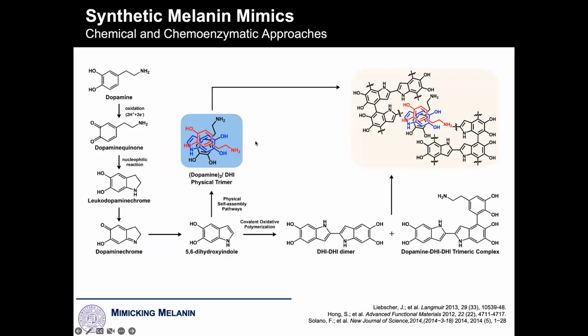We have two effects then. We have both covalent bond formation between these rings, and you can see some of the dimers and trimeric complexes that are forming. These go on to make tetramers, and remember, they're three-dimensional polymers, so they're highly cross-linked. They're also cross-linked in the supramolecular sense. So beyond the molecule itself, the materials are stacked. So there's pi stacking as well as covalent bond formation. But you end up with this polycatecholate, there are hetero aromatic rings present, catechol groups present, so they can coordinate metals. Just keep those structures in mind as we talk about some of the architectures.